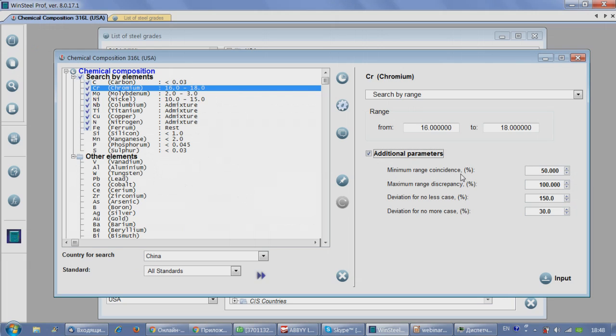And this is by default, but you can change this coefficient. For example, if you input 80, it will be a harder condition. And 80%, it will be from 1.6, and so on. If you input 30, it will be a softer condition. In case, for example, you input 50 but don't find equivalents, you can return, change this coefficient, and try to find again. And the second one, the maximum range discrepancy, by default is 100%. So it is possible that the range will be from 14 to 20 for chromium. And besides these two coefficients, we have two others. This is deviation for no less case and for no more case.